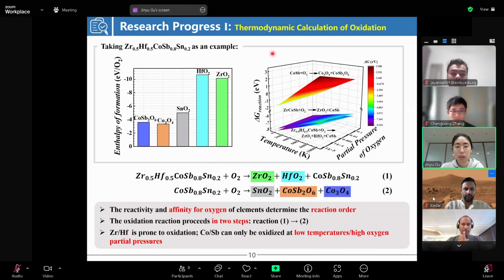We then performed first principles calculations in thermodynamics. The formation enthalpies of different oxides in DOL vary greatly and thereby determine the oxidation order. So the oxidation reaction will proceed in 2 steps. By calculating the Gibbs free energy of the 2 reactions as a function of temperature and oxygen partial pressure, it was found that zirconium and hafnium can be easily oxidized, while cobalt antimony is only oxidized at low temperatures or high oxygen partial pressures. Therefore, the cobalt antimony can remain unoxidized and coexist with the zirconium and hafnium oxides in DOL.